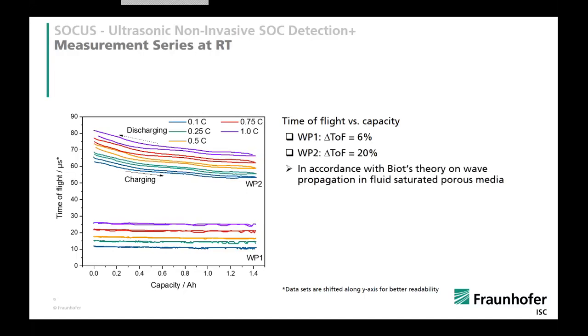So what we then calculated is that especially for wave package 2, the change of the time of flight is in accordance with Biot's theory if you apply the elastic parameters for the charged and discharged state mentioned before. During charging, you have quite a monotone slope, independent of charging rate for all 5 sample cells, which is quite useful and easy as input for machine learning in order to estimate cell properties.